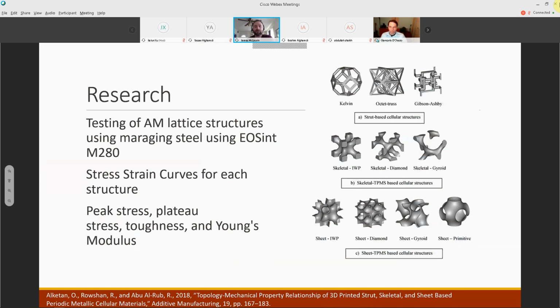With our research, we looked into what data we could find about these lattice structures. We found a really excellent article where a team had tested these lattice structures with maraging steel using the EOS M280 3D printer, which is what we'll be using. So it was a great direction for us to take our project. It gave us stress strain curves for each structure, and then it gave the peak stress, plateau stress, toughness, and Young's modulus.